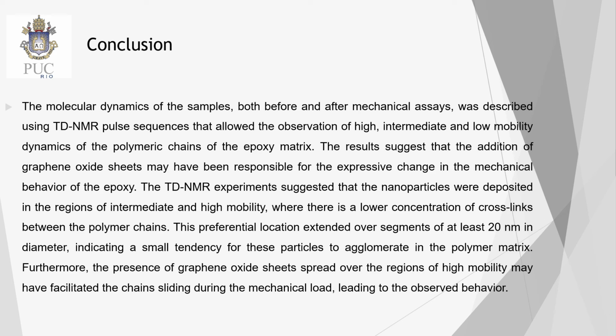So, the conclusion is that the molecular dynamics of the samples, both before and after mechanical assays, was described using TD-NMR pulse sequences that allowed the observation of high, intermediate, and low mobility dynamics of polymeric chains of the epoxy matrix. The results suggest that the addition of graphene oxide sheets may have been responsible for the expressive change in the mechanical behavior of the epoxy.